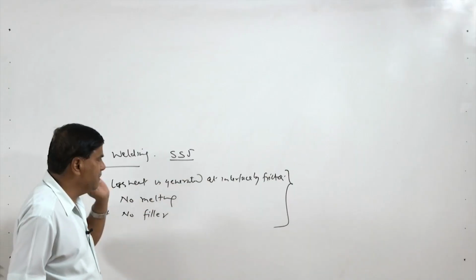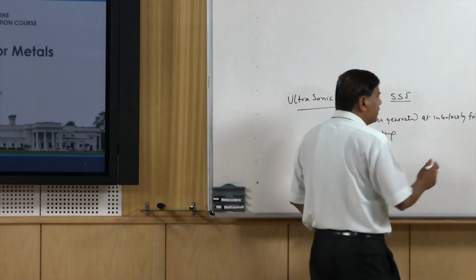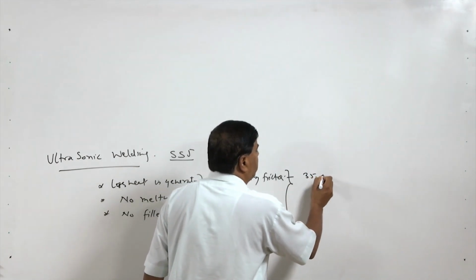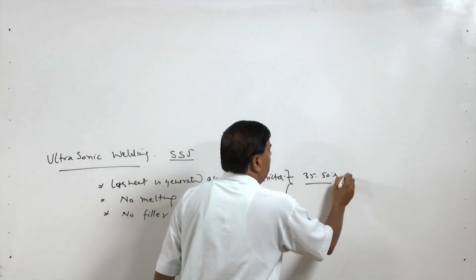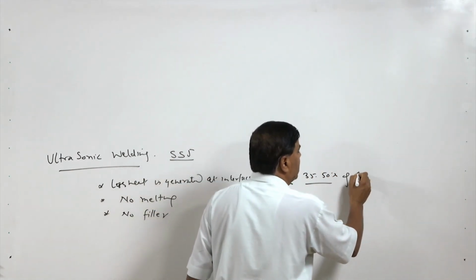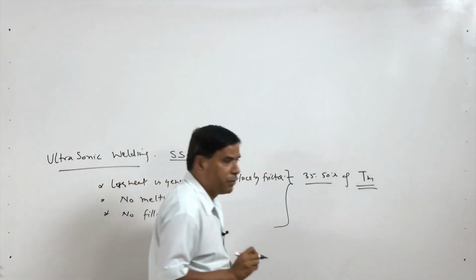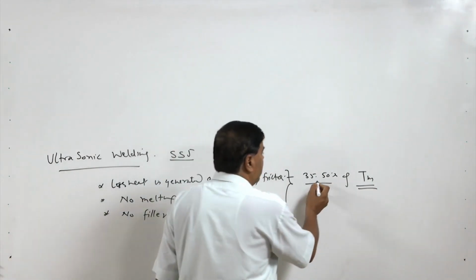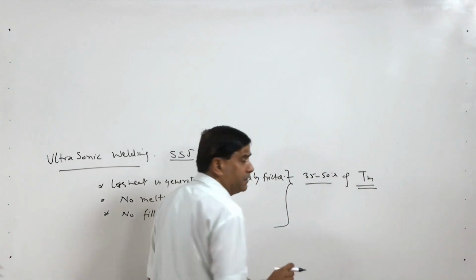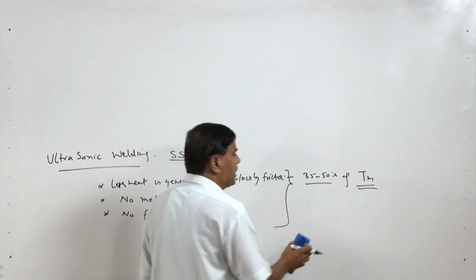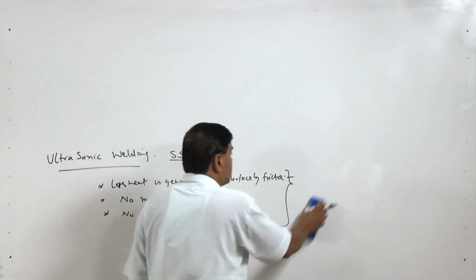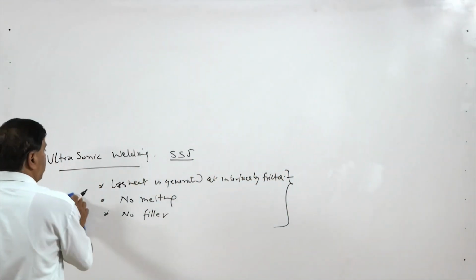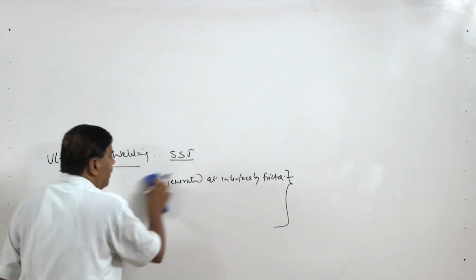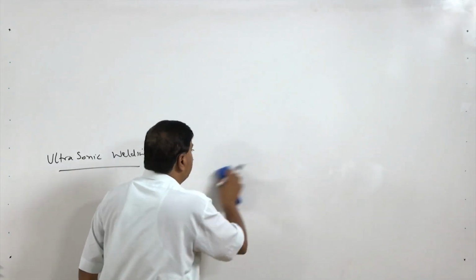So, very little heat is generated, at the most 35 to 50% of the melting point temperature in absolute scale, that is, in Kelvin. This is the maximum temperature rise due to the frictional heat generated in the course of the welding. And this heat helps to soften the metal and facilitates the plastic flow of the metal at the interface.